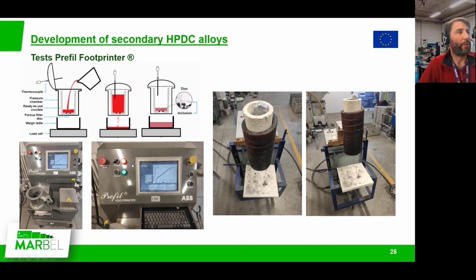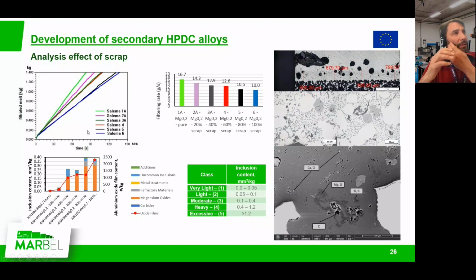We measure this inclusion content with an alternative technique, the pre-filled footprinter, that is provided by one of the project partners. With this technique, you melt the aluminum inside the crucible and you get it filtered. There are several outputs you get from this equipment. The filtrating rate is decreased quite a lot when we are using more scrap. The presence of inclusions left in the filter is also increased with the amount of scrap.